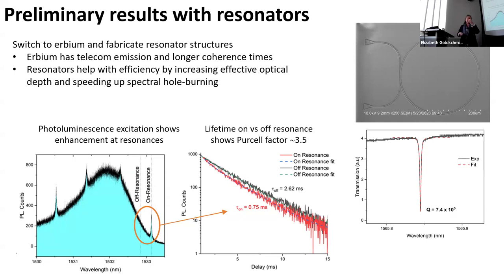And in fact, because they're not the same size, the inhomogeneous broadening is enormous, nanometers wide, right? I was showing you in those europium crystals, inhomogeneous broadening of some gigahertz. Here that's inhomogeneous broadening of, I don't know, is that a terahertz? Something huge, right? That's because we've got more defects because the doping is high, but also the defect is huge, because you've just really strained that lattice by shoving an erbium in a lithium site.